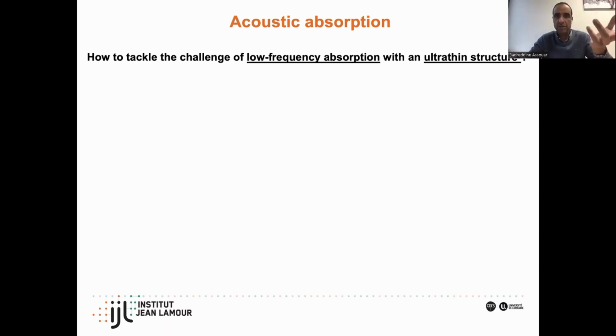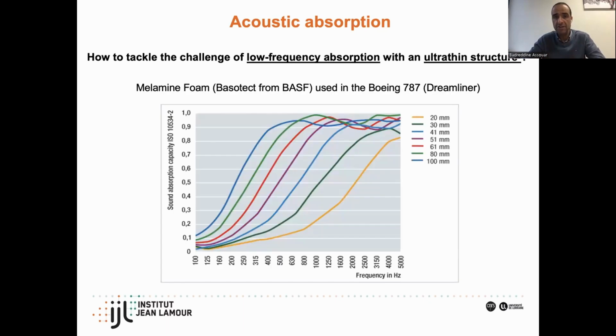And so the question is, how to tackle the challenge of low frequency absorption using very thin or ultra-thin structures. So this is the very famous absorbing property of the well-known melamine foam, which is actually used in the Dreamliner. So here you have the acoustic absorption versus the frequency for different thicknesses of this foam. And as you can see, if we deal with a little bit higher frequency, which is above, let's say, 1 kilohertz or even above 500 hertz, it's fine. If you have a 10 centimeter thick foam, it's fine.